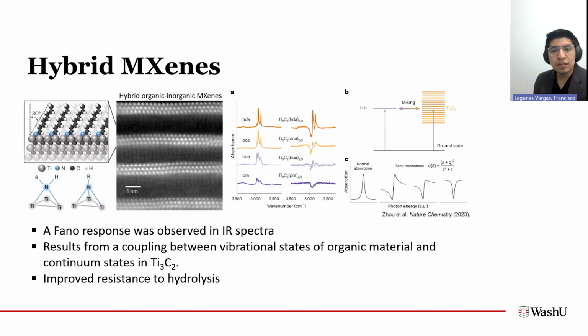So we observed some interesting optical phenomena in IR spectroscopy. Specifically, we observed a Fano resonance, which is a result of the coupling between the vibrational states of the organic material on the surface of these h-MXenes and the continuum states in the Ti3C2 lattice. And we also saw some practical improvements to these materials, such as an improved resistance to hydrolysis. And again, if you're interested, I'll refer you to this paper. This paper is really showcasing the fact that we can synthesize these materials and talking a little bit more about some of their fundamental properties.